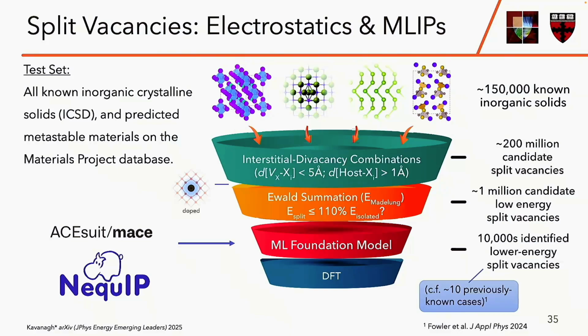So I wanted to go bigger and see if I could demonstrate the presence of these defect states across an even wider range of material space, leveraging this drastic machine learning acceleration. This machine learning acceleration allows me to scan all known crystalline inorganic solids given in the ICSD, as well as all predicted metastable materials on the Materials Project database.